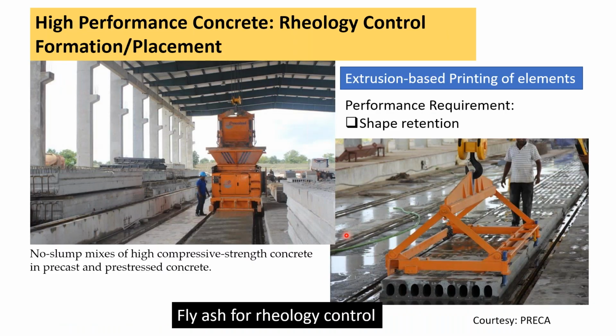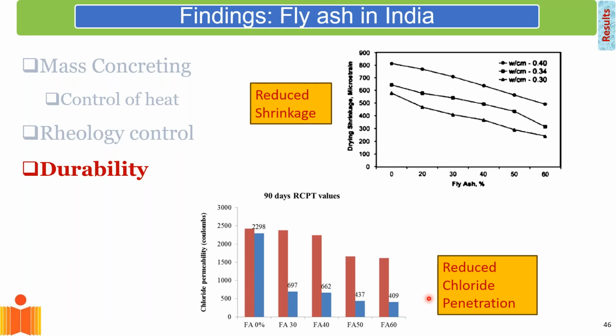Another place where fly ash is an absolute must in controlling the flow is in the use of precast concreting, particularly where you have these hollow core slabs that are being produced. The hollow core slabs are typically produced in an extrusion type mechanism. After the slab is extruded, these holes are supposed to keep their shape. The material should not collapse on itself and close the hole. So that again requires fly ash. The other places where fly ash has been used quite considerably to provide a pumping solution is in the construction of, of course, One World Trade Center, where fly ash was used to get some control in pumping, and also in Burj Khalifa, where concrete is pumped to a height of 601 meters.